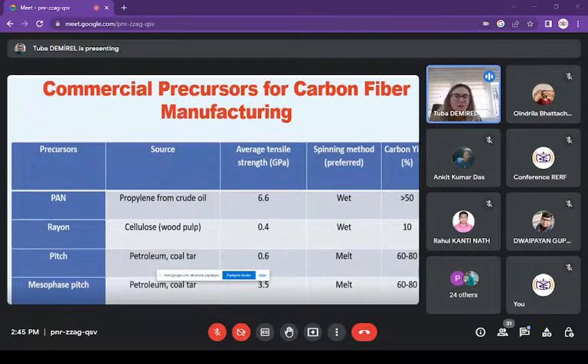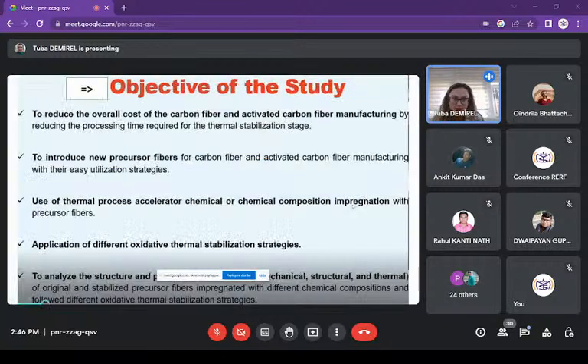Commercial precursors for carbon fiber manufacturing are PAN (crude oil), rayon (cellulose), pitch (petrol or coal tar), and mesophase pitch (petrol or coal tar). Very important is the average tensile strength, and PAN is better than the other raw materials, and its carbon yield is bigger than 50 percent.